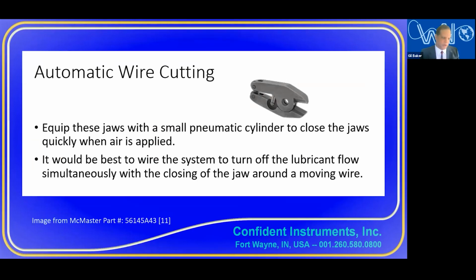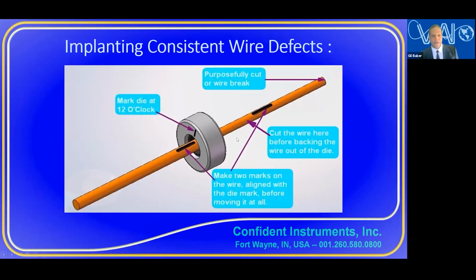So for the methods of measuring cast, I'm just going to touch on 2 simple and low-cost ones. You can either create a break in the wire while the machine is running by running the wire through a jaw that's going to clamp pretty quickly, pneumatically, for example. Or you could do your analysis when there's a natural wire break. In those cases, you're preserving what's going on in the deformation zone downstream of the break. So you preserve that, and now we can look and see what the deformation zone looks like before you have to pull the wire out of the die.